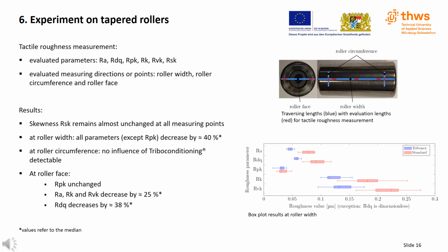Now I would like to present the results of the tactile roughness measurements. The evaluated parameters are Ra, R delta Q, the parameters from the material ratio curve, RPK, RK and RVK, and the skewness RSK. In the upper right figure you can see the selected traversing lengths in blue and the evaluation lengths in red. All tapered rollers were measured along the roller width, on the roller circumference, and on the roller face.